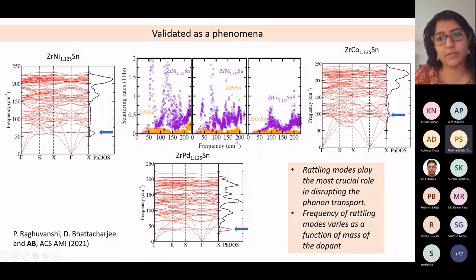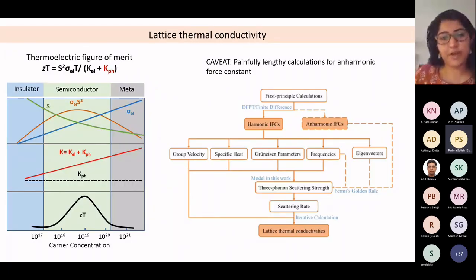However, if you have a kind of doping where the frequency goes into this type of region without hampering the acoustic mode, then this situation is not as good, because the scattering lifetimes are disrupting the phonons, but not as much. So we proceeded further. So here we show a caveat.